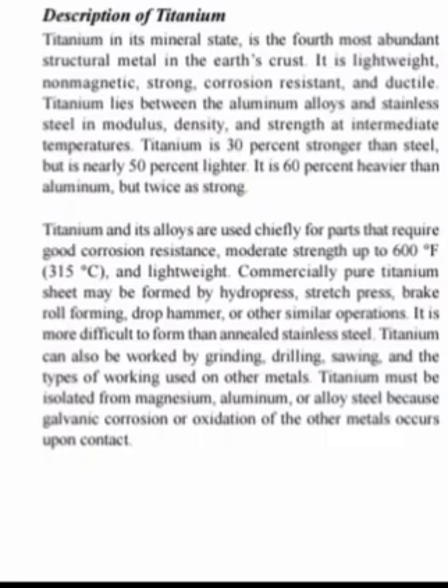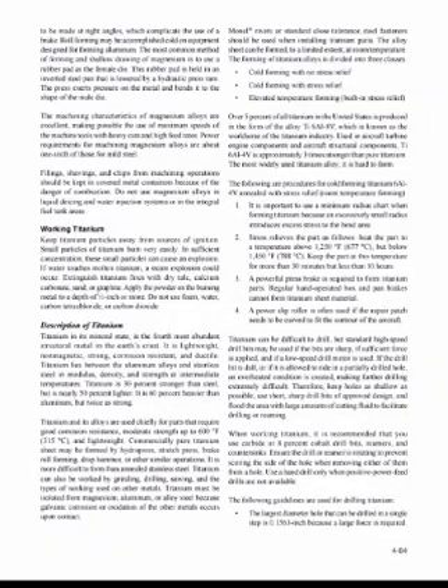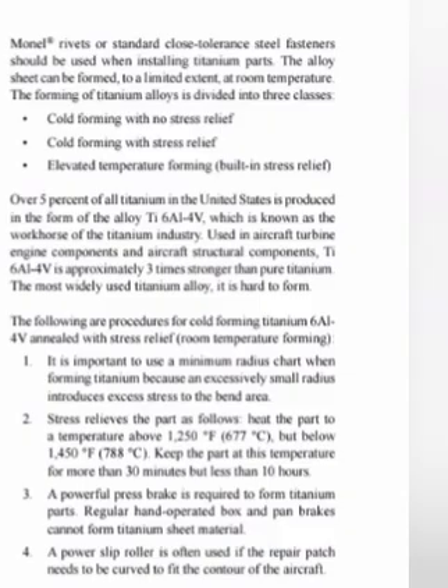Titanium must be isolated from magnesium, aluminum, or alloy steel because galvanic corrosion or oxidation of the other metals occurs upon contact. Monel rivets or standard close tolerance steel fasteners should be used when installing titanium parts.